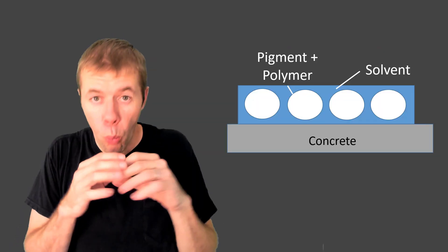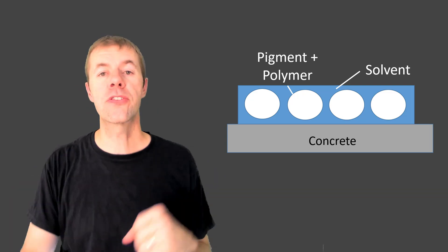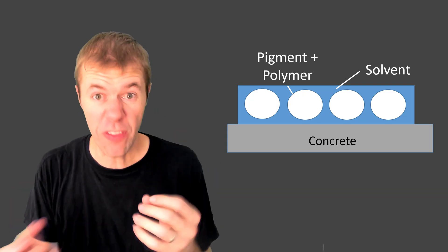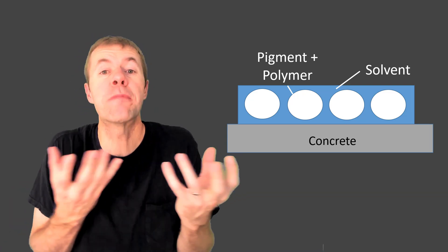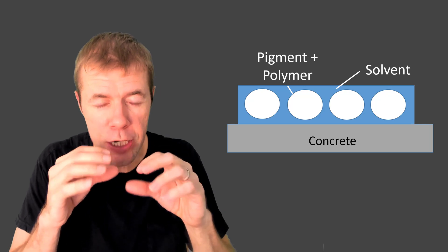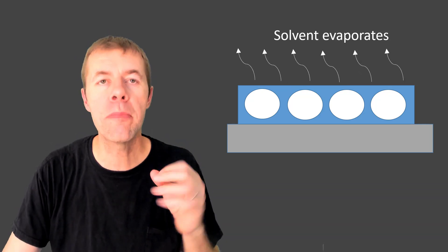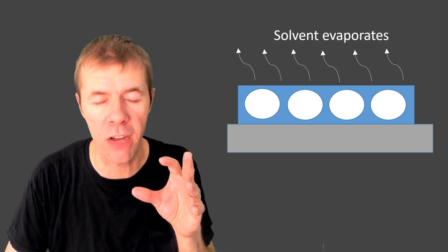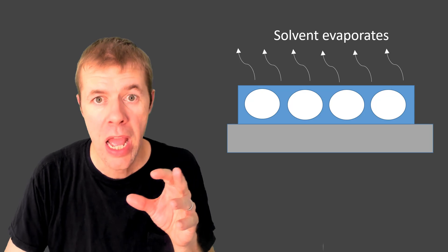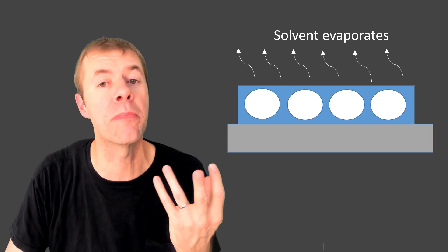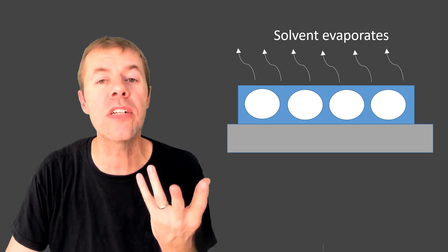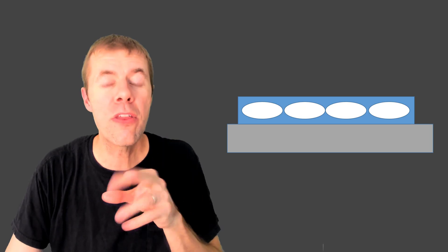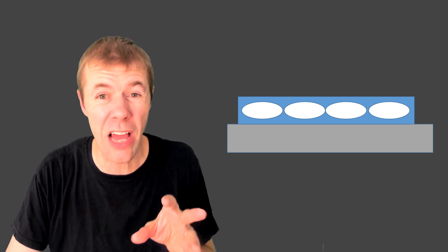Now let's explain how curing compounds work. When they're applied to the surface you can have a solvent. That's something that they're suspended in and then you have your pigment and your polymer and over time your solvent is going to evaporate off the surface. And that's the stuff you can smell sometimes. And once it starts to leave then the polymers kind of get closer together and then eventually they bridge and form a layer on the surface of your concrete that helps hold moisture in. This is like painting. If you've ever painted a room it's the same type of thing.